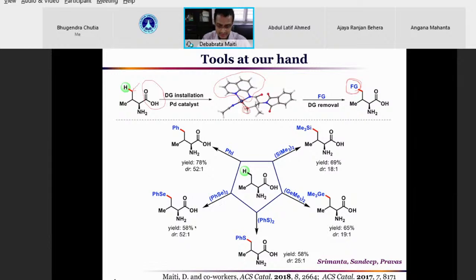Well, as it turned out, this is a general approach, and we are able to selectively functionalize this gamma CH bond. This reaction works quite well with very good levels of stereoselectivity, and moderate to good to excellent yield in selective cases. So the major advancement has been that at the gamma position of acid, it could be amino acid or simply other acid, we can selectively form a new bond without touching alpha, beta, delta, or any other bond that is present in the molecule. This is once again similar to what we see in enzymes, but by doing so in a synthetic setup, we can certainly synthesize molecules which can be used in the industrial sector as well as in academia. These are once again simple amino acids, cheap, readily available, and very, very useful for life.